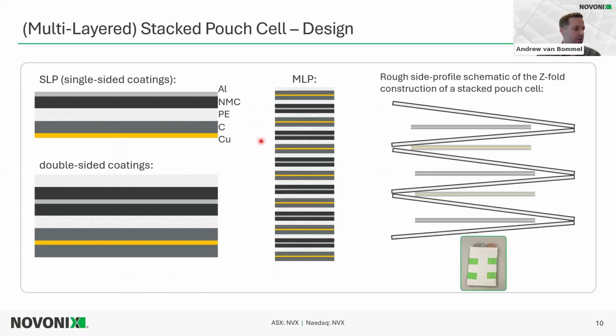So looking at the multi-layered stack cell design, if we looked last at the single layer pouch that had single-sided coatings, the multi-layered stack cell would have double-sided coatings. So starting from below again, here's the copper coated on both sides with graphite, polyethylene separator, and the aluminum coated on both sides with NMC. Here's a typical multi-layer pouch cell in the side profile. So we would have 7 anodes and 6 cathodes. So here are the bookended anodes on each end, and they're separated by that polyethylene separator. And this would be about a 1 amp hour pouch cell with the smaller, around 42 by 60 millimeter sized